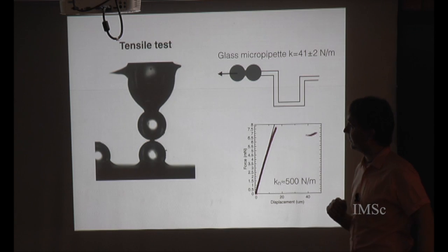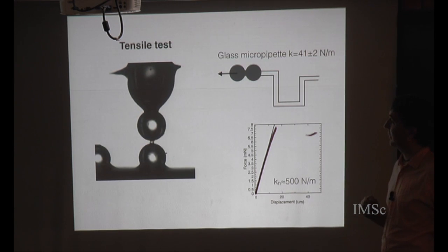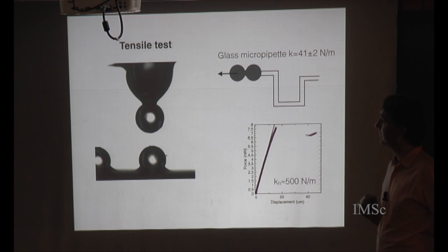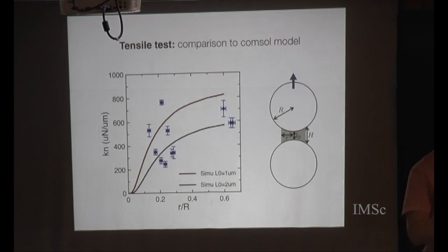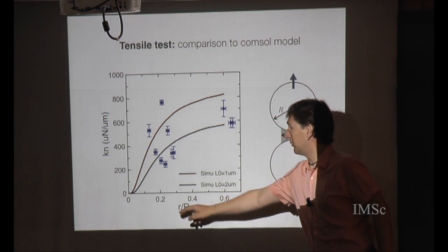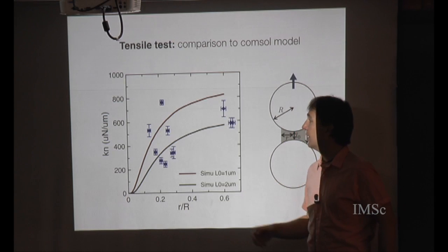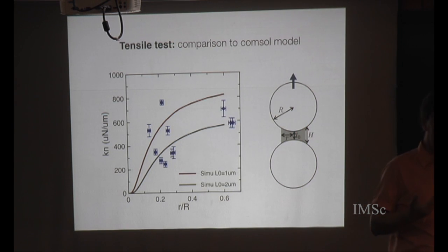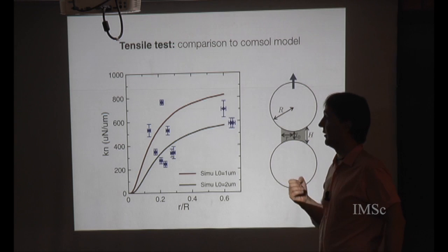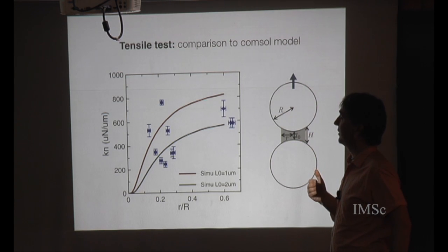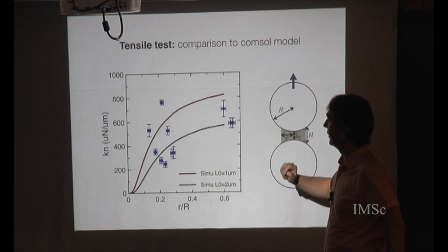We can monitor the position of everything to get a stress and strain relationship out of this. And you can get basically the constitutive relationship for a single bead. This is the scatter that was asked earlier. These are individual measurements. This is the radius of the bridge and the radius of the bead. It's basically whatever you can make on this type of scale. You basically get a bridge that size, and then you test it. These are hard to manufacture with any regularity. So you make a few dozen samples, you test them, and you get scatter like this.